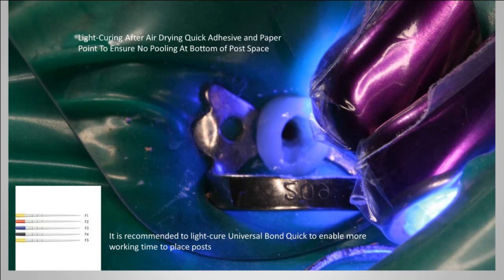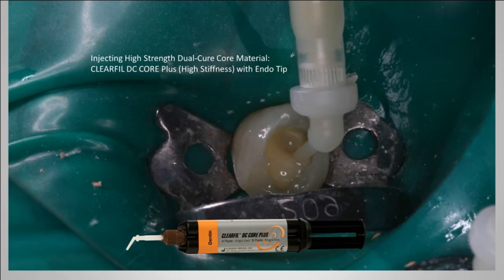We air dry it first, and then you can get pooling down in the bottom where you can't get that air. So it's recommended you take a paper point and put it down in there, and it will absorb the bonding agent, pull it up out of there so you don't get that puddling. Because there's nothing worse than putting a post in there and it looks real good, and then you take an X-ray of it and you have this gap between your fill and the post, and you think, what in the world happened? Well, more than likely that's bonding agent down in there. It's blocking it up. You really did get the post as far as you could, but you cured the bonding agent in there. So get it out of there, and light cure it.